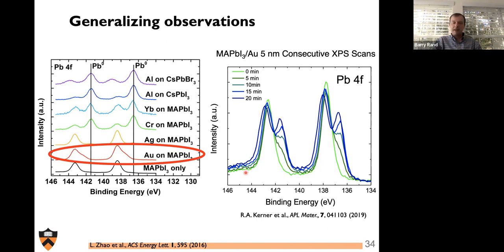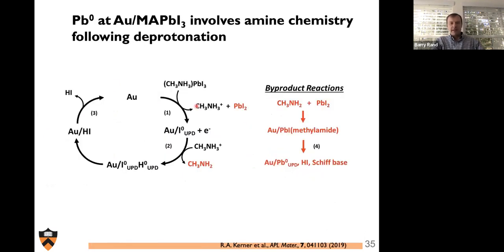So where initially you have no presence of lead zero, upon further measurement time, lead zero clearly emerges. And this is an artifact of formation of amines. Here's the cycle of that, where gold acts as a catalyst. What happens is gold attracts iodide, and it extracts iodide from the system. When it does that, it eventually leads to the formation of HI, which goes away. And when HI is formed, it deprotonates methylammonium, and any methylamine that is formed in the presence of lead iodide will form this lead amide bond, which, as we've said, is completely unstable and will lead to the formation of lead zero.